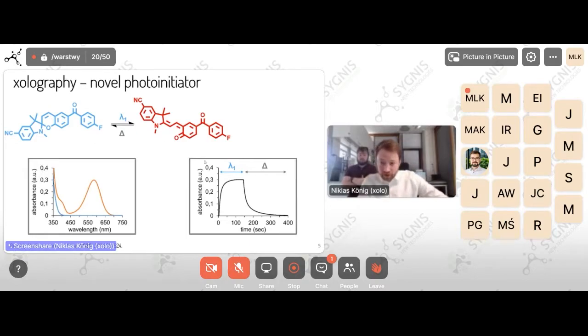We can follow this process by tracing the concentration of merocyanine, by tracing the absorption at 600 nanometers, and this is what we did here. We see that when you shine lambda 1, the first wavelength, on a solution of spiropyran, then the concentration of the merocyanine goes up until a certain point where the photo reaction is as fast as the thermal back relaxation. So you have an equilibrium concentration. And then when you switch off the light, only the thermal back relaxation takes place, and immediately the concentration goes down, and the half-life is just some seconds here.